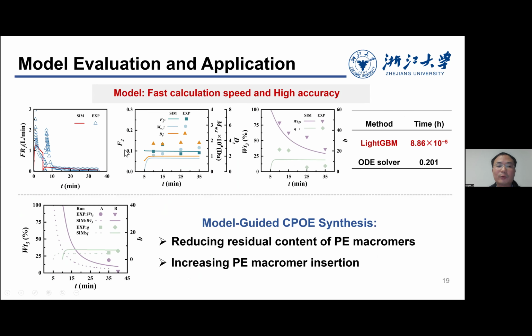And this is what we have done. You can see if you use the machine learning LightGBM model, we can significantly reduce the time for the calculation. And our results are a good fit with the experiment. Here is the flow rate of the ethylene, and this is the calculated one, and this is the cumulative composition of the octene inside the chain.